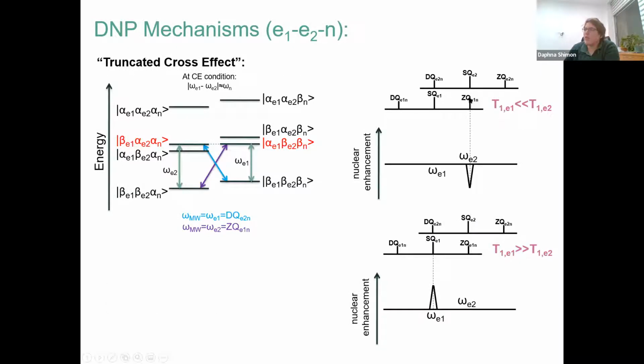If there are two electrons and you're irradiating on electron 1, and if electron 1 has a very fast relaxation time, you can't irradiate on it and affect it. You can't saturate it, and so you don't get enhancement. But when you irradiate on electron 2, which has a slower relaxation time, you can saturate it and you can get enhancement. So that would look like a cross effect that looks like a negative Overhauser effect. And in the other case, if the fast relaxation is on electron 2, then you would get only positive enhancement when you irradiate on electron 1.